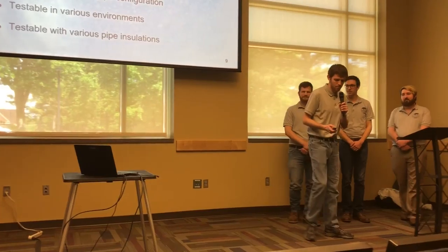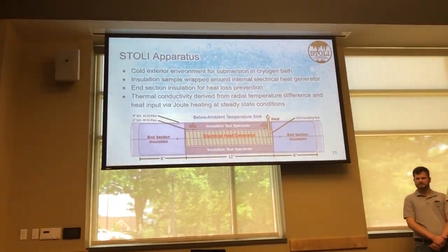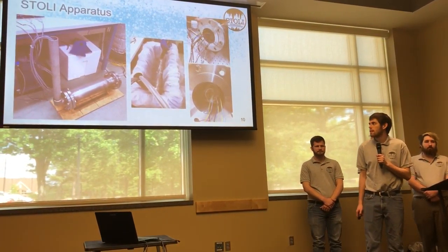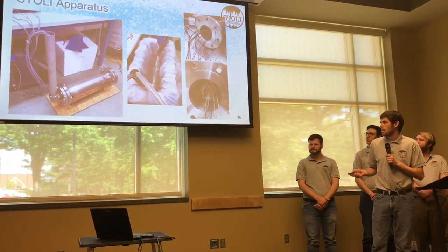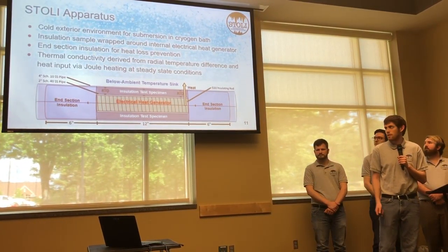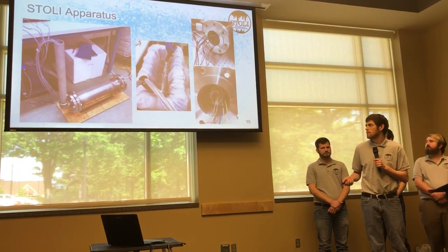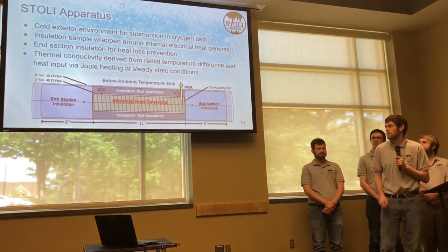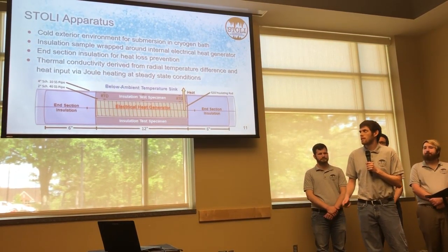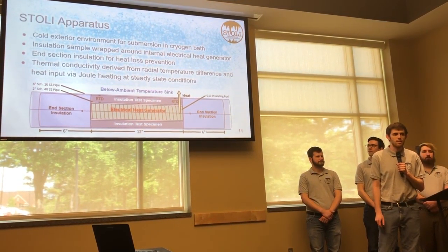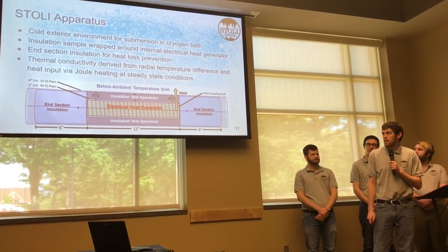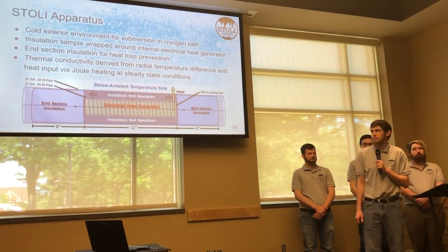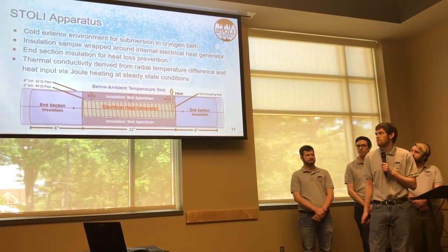I'll be talking about our apparatus that we've been designing and working on for the past two semesters. Here is a simplified schematic of the function of our apparatus. Essentially, we dunk it in a cold bath to isolate it from the external environment. We have the insulation sample around an internal electrical heat generator, and we find the thermal conductivity of the insulation by measuring the radial temperature difference across it from the heat input of the heater.